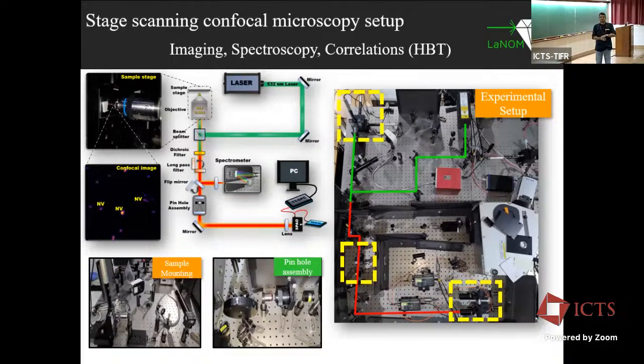Is it possible to put these defects in some array, maybe not in diamond but in another material platform? And also you're working with super hard materials, so is it possible to engineer defects at specific locations? In the super hard approach, we make diamond samples and test whether we have a single NV center. We did Hanbury Brown and Twiss experiments and didn't get any dip like single photon emission, so those are all mostly ensembles. Once we are able to create them preferentially and are confident that we got a single NV center, then probably we can make it an array.